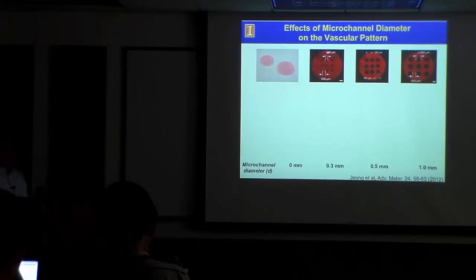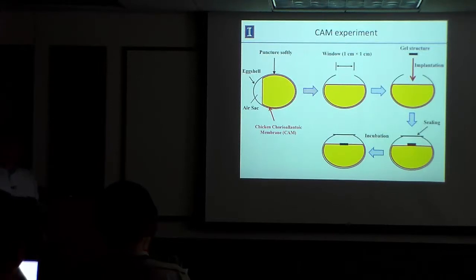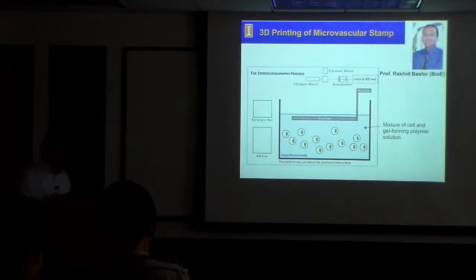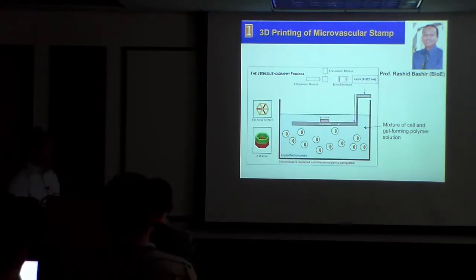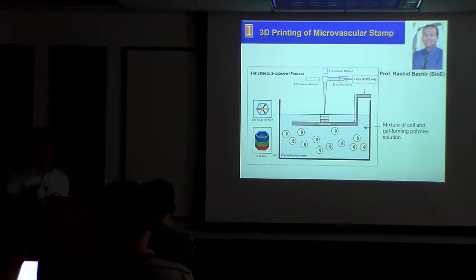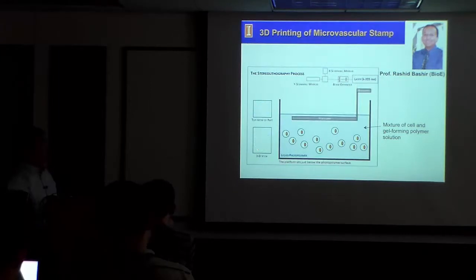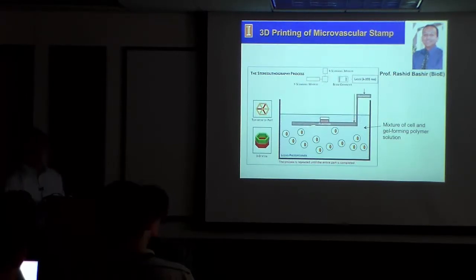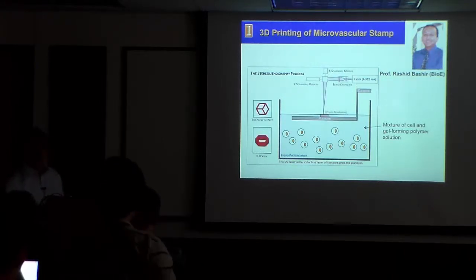To assemble hydrogels with controlled microchannel diameter, we collaborated with Professor Rashid Bashir in bioengineering, using 3D printing to incorporate controlled-size holes in the cell-encapsulating hydrogel. The 3D printing setup used a bath containing cells and gel-forming solutions, an elevator moving along the Z direction, and a laser unit moving along the XY direction to activate cross-linking reactions. Using computer software to orchestrate XY laser movement with Z platform movement, we generated predefined hydrogel forms encapsulating cells via in situ cross-linking.